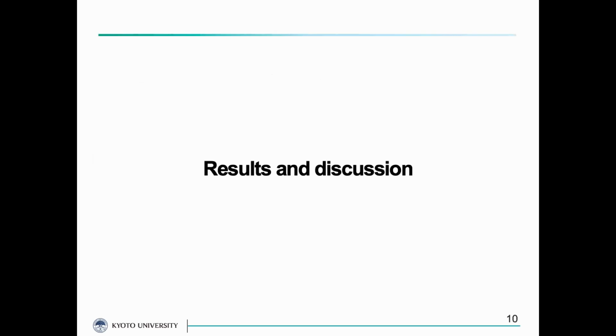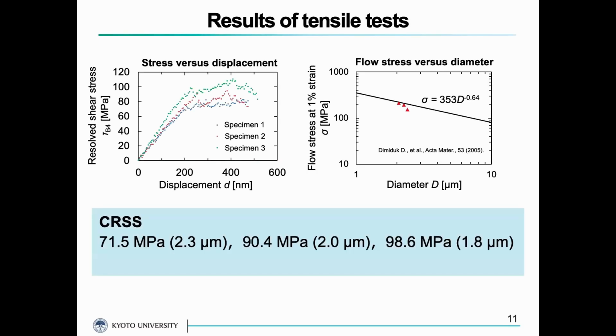So now let me talk about the results and discussion of this research. First, we conducted 3 tensile tests, and an obvious elastic-plastic transition was observed. CRSS was evaluated to be in the range between about 70 and 100 megapascal, and the result was in very good agreement with previous research from the stress versus diameter plot. We can state that we can confirm the reliability of our experimental system.